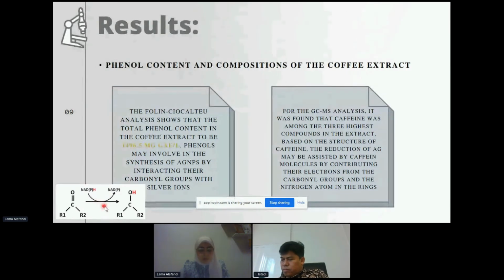First step or first stage is to start with the reduction of hydroxyl groups, followed by the oxidation of them to carbonyl groups, then a release of reactive hydrogen, which is responsible for the reduction of silver. In addition, the carbonyl groups also could prevent agglomeration after binding to the surface.